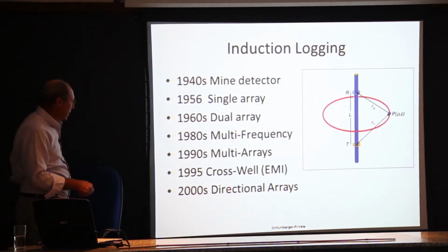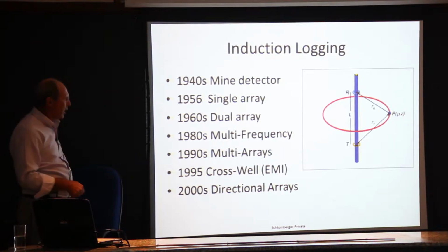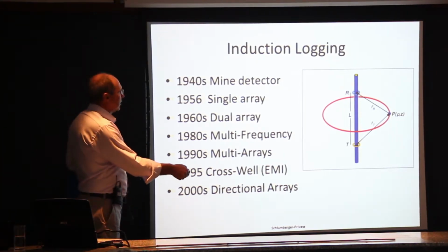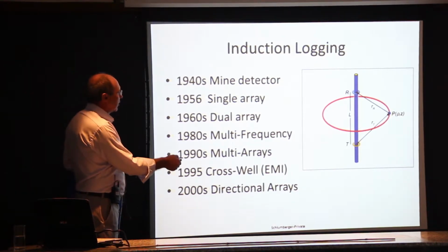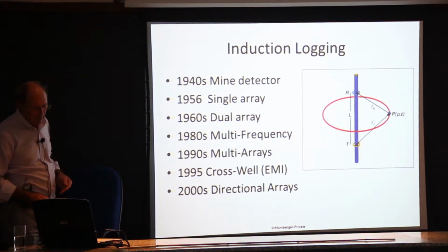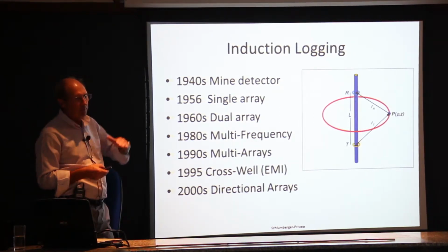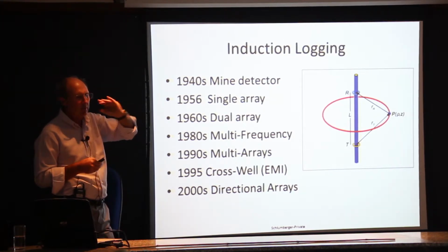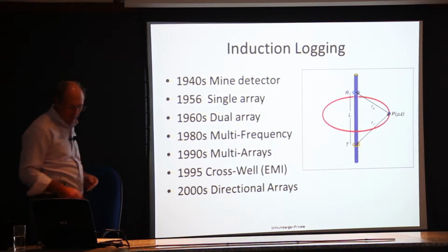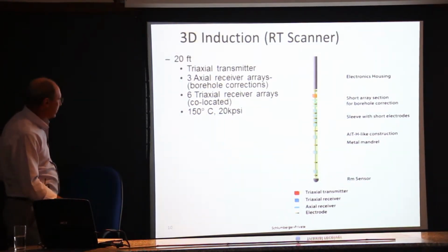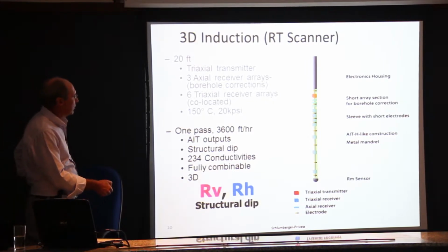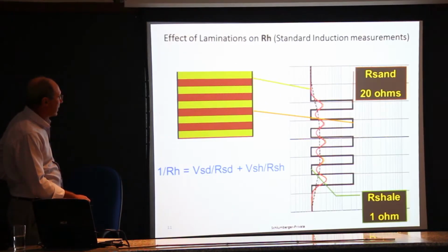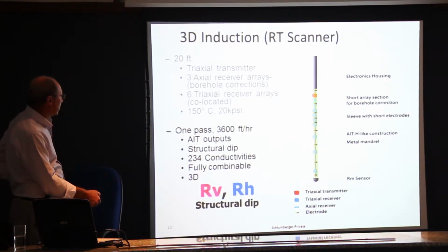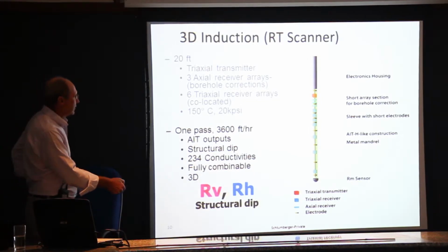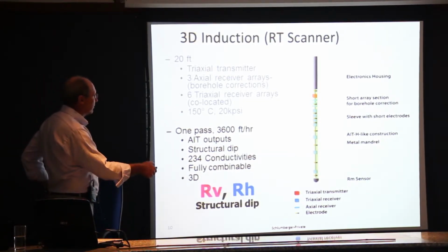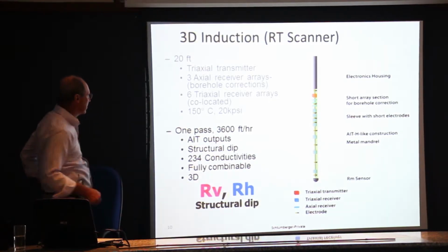By the late 90s, early 2000s, though, we moved to what we call triaxial inductions, where you not only have a current ring in this direction, but you can have one in this direction and then in this direction. And this is a big advance, especially for above the salt in the turbidite formations, where you have layers of sand and shale. But also it's quite helpful in the pre-salt as well. And this is a schematic of the newest tool, where you have these additional triaxial receivers to give you information, not just from current flowing in this direction, but from current flowing in this direction and current flowing in this direction as well.